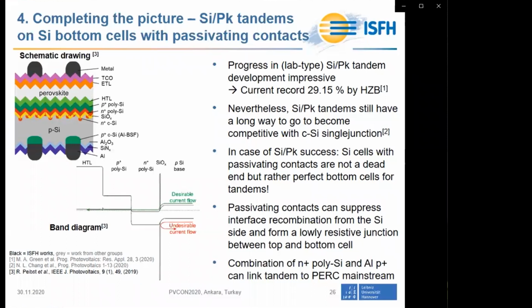Nevertheless, let's assume that they are successful. The question arises whether silicon cells with passivating contacts are at their end. And our answer to this question is, of course, no, they are not at their end, but they rather form perfect bottom cells for this tandem approach. For example, in this two-terminal structure as shown here with the silicon bottom cell and the perovskite top cell, you will need an interface passivation at the interface from the silicon side here. This interface should not only be passivating, but it should also collect one carrier type and transport it to the top cell. And in this case, those are the electrons. They should be collected and transported to the top cell, while the holes should be blocked at this interface.